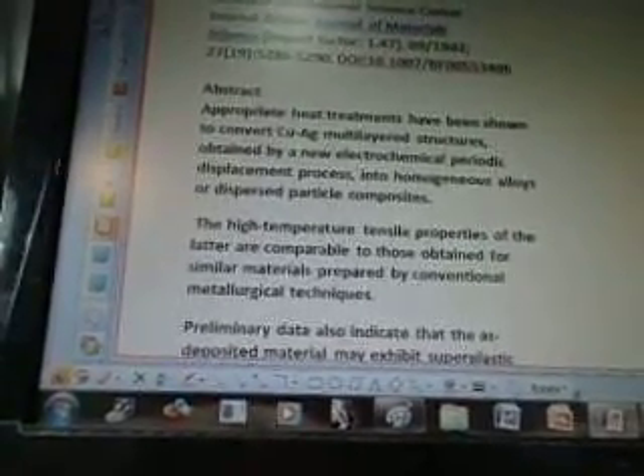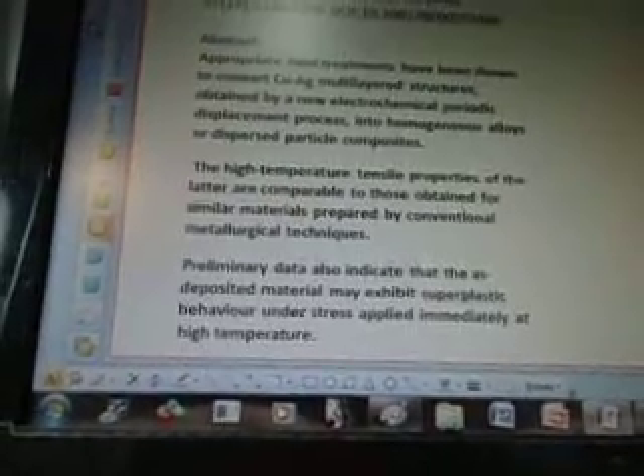Abstract. Appropriate heat treatments have been shown to convert CuAg multi-layered structures obtained by a new electrochemical periodic displacement process into homogeneous alloys or dispersed particle composites. The high temperature tensile properties of the latter are comparable to those obtained for similar materials prepared by conventional metallurgical techniques. Preliminary data also indicate that the as-deposited material may exhibit superplastic behavior under stress applied immediately at high temperature. And that's from ResearchGate.net.